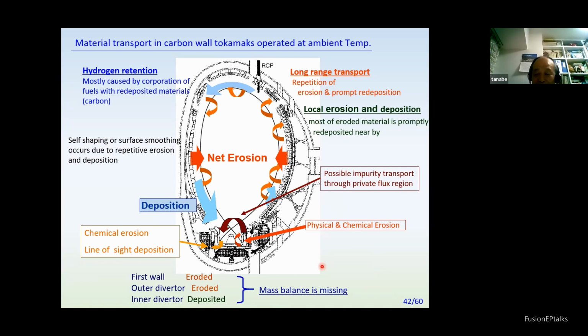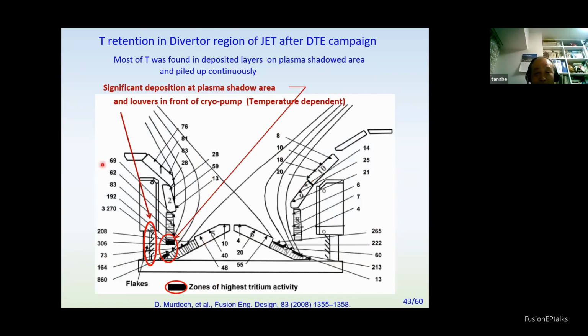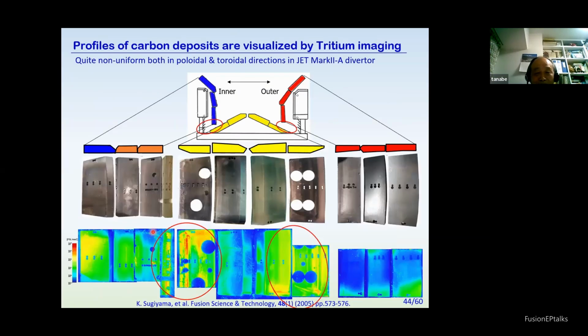In any way, most of this deposition retains hydrogen, mostly caused by incorporation of fuel with redeposited materials around here. This is shown here - in the JET experiment, they used tritium, and found a lot of tritium deposited together with carbon on the plasma shadowed area, shown clearly in the tritium imaging. This red part retains the high amount of tritium here, mostly in the plasma shadowed area.